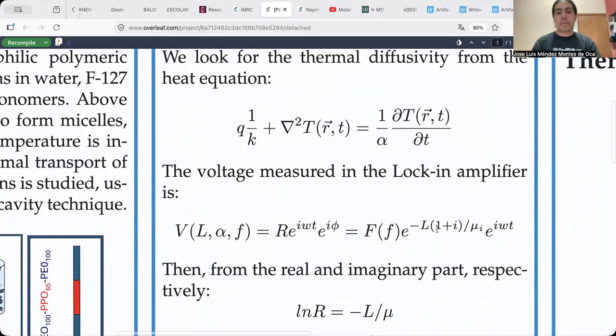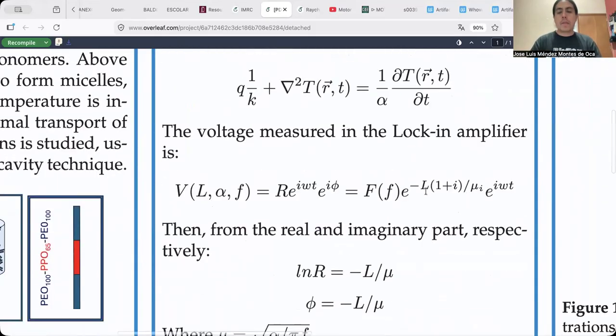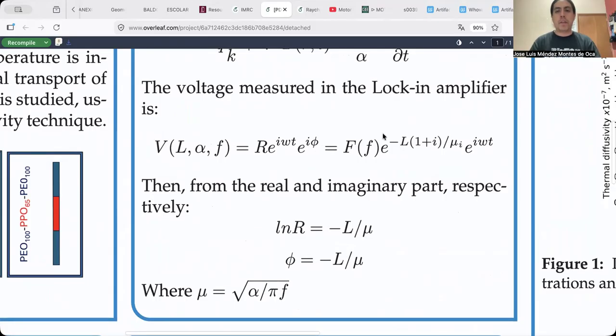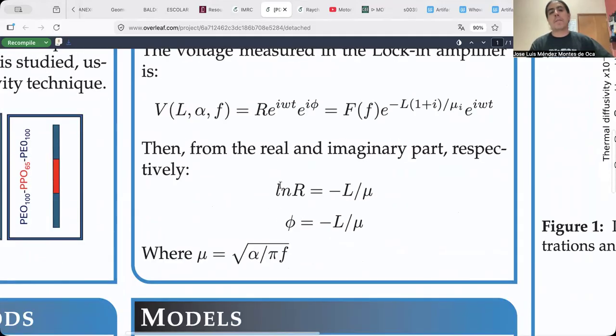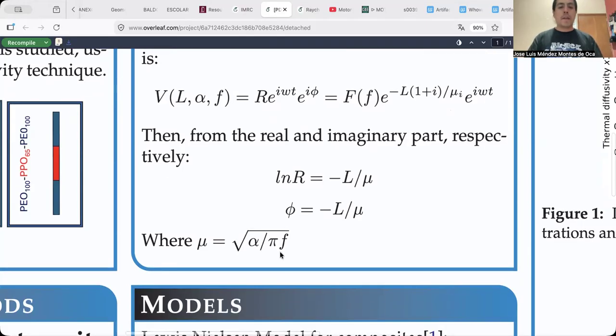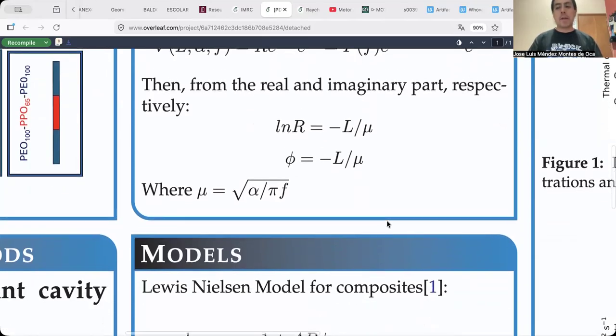And in the thermally thick regime, it can be simplified to this form of exponentials with a function dependent on the frequency. And the real part and the imaginary part of these equations can be related. And it can be plotted, for example, the logarithm of the amplitude versus the depth of the sample L, or can be plotted the phase of the signal versus the depth of the sample L, and from the slope of these curves the thermal diffusivity of the sample can be obtained.